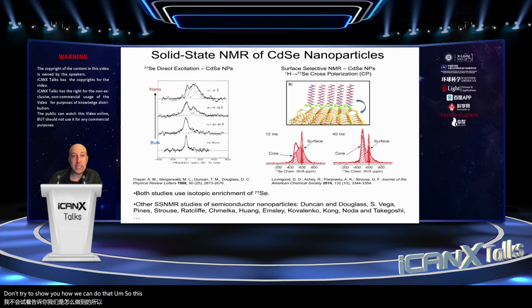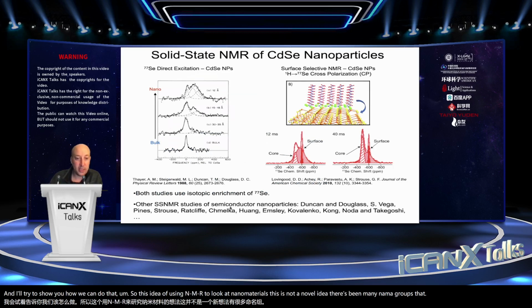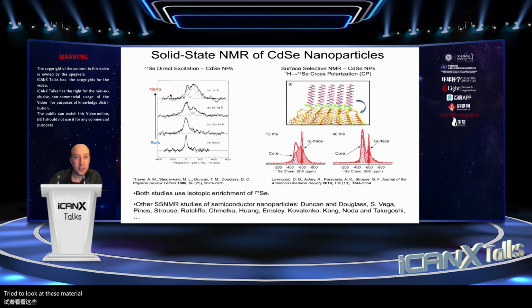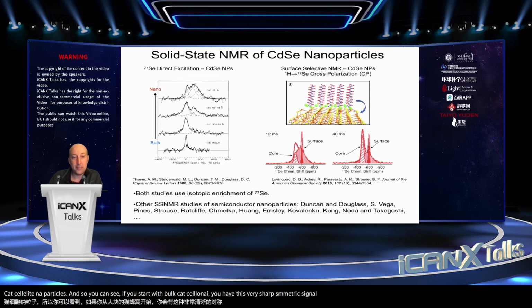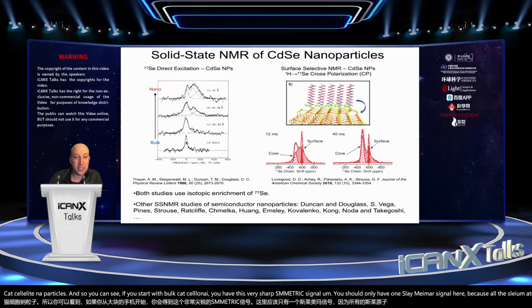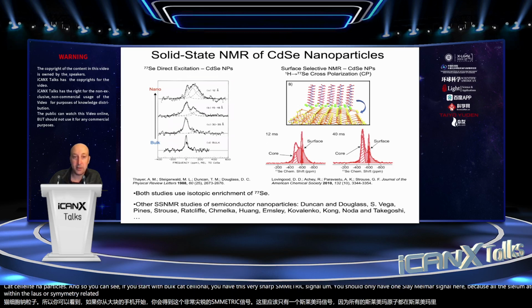So this idea of using NMR to look at nanomaterials, this is not a novel idea. There's been many NMR groups that have tried to look at these materials. So this is a classic example from Bell Labs, where they did some selenium-77 NMR experiments on cadmium selenide nanoparticles. And so you can see if you start with bulk cadmium selenide, you have this very sharp symmetric signal. You should only have one selenium NMR signal here because all the selenium atoms within the lattice are symmetry related and are equivalent to one another.